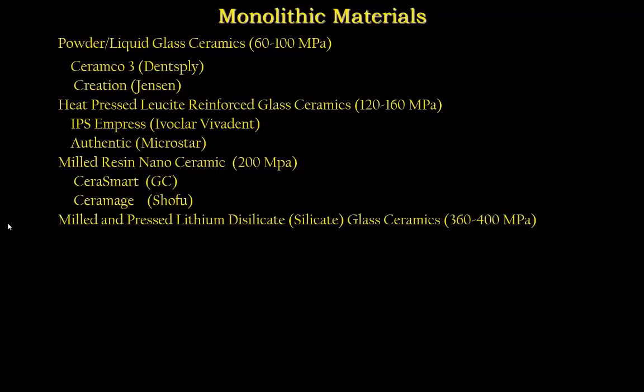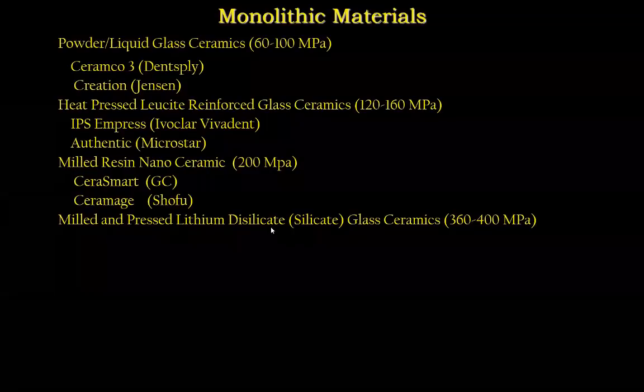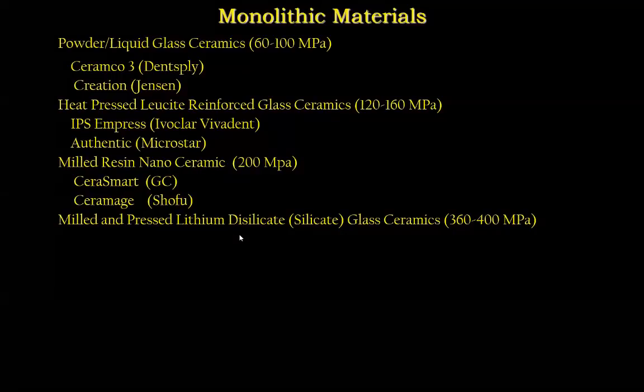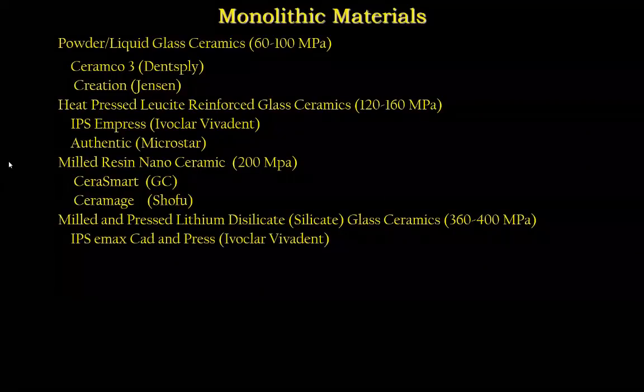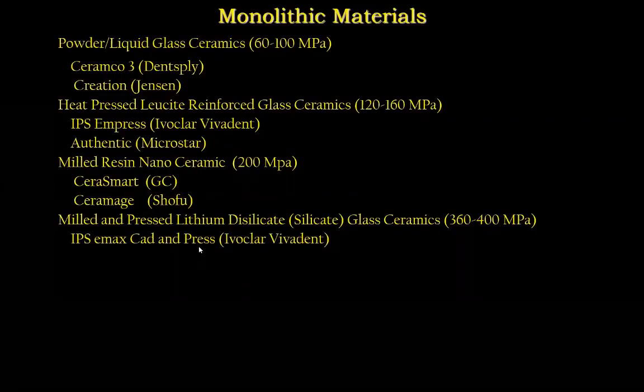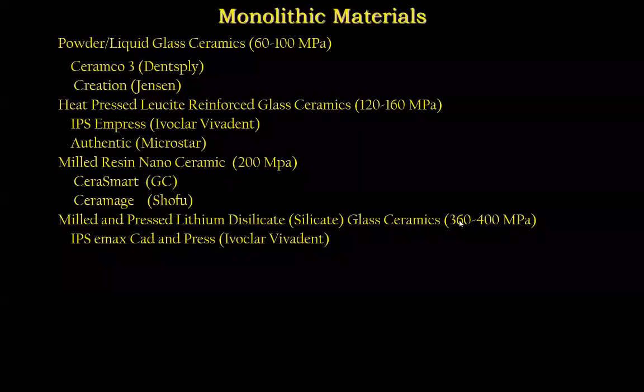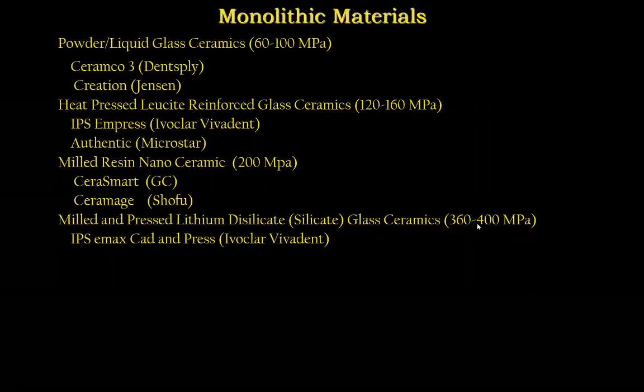But the next big breakthrough, in my mind, one of the major breakthroughs that we've seen in dentistry, was the milled and pressed lithium disilicate. And today we see, so Ivoclar came out with an Emax CAD, which is the milled, and the Emax press, which are the ingots that were done just like Empress. This was twice as strong, or 3 times as strong. The CAD was 360 megapascals. The press was 400 megapascals.